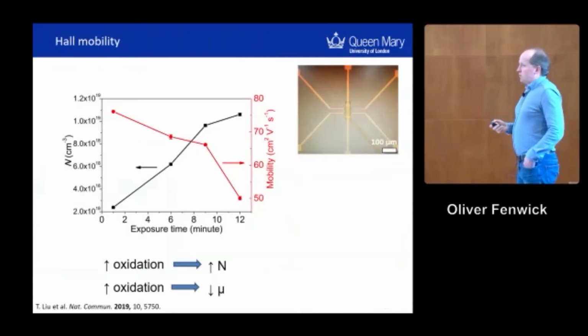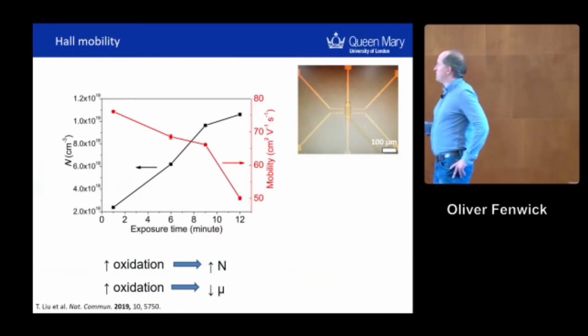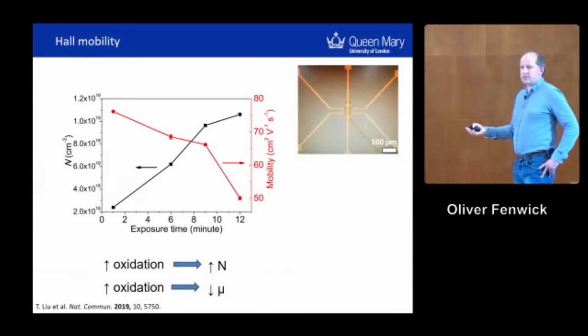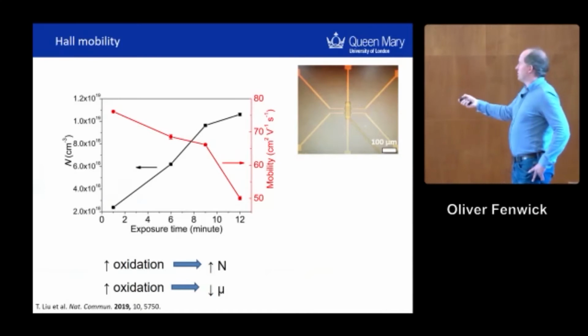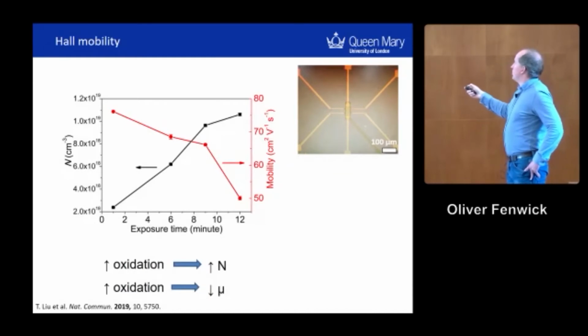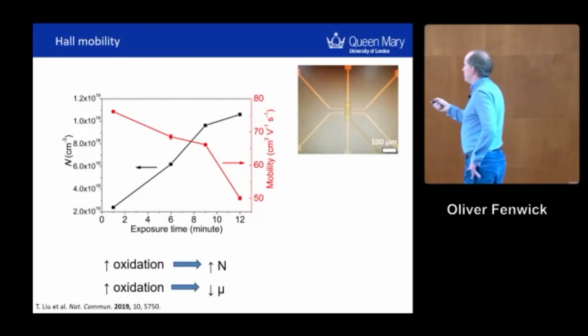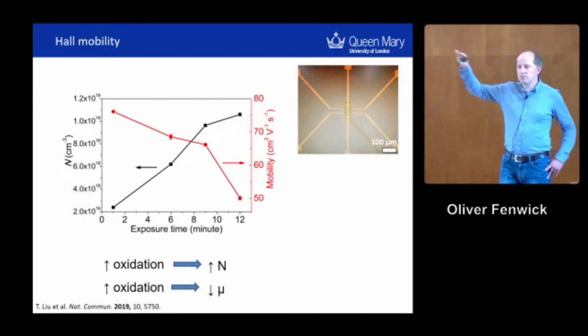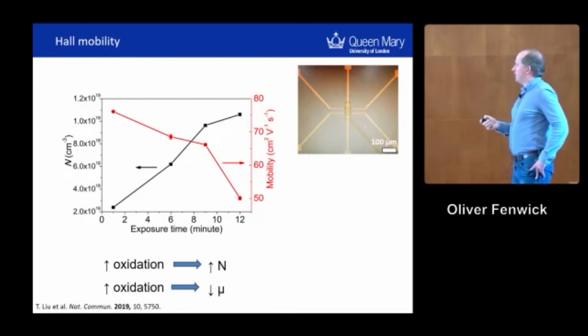So what's going on? Well, if you see an increase and a decrease, it's probably a competition between 2 different factors. In electrical conductivity, you've got the number of charges you're generating and the mobility of those charges. The product of those gives you the electrical conductivity. Indeed, if we do Hall measurements on a patterned piece of this material, you see the number of charges constantly increasing as you expose the material to air. That's the black curve. On the other hand, the mobility is decreasing, and the rate of decrease accelerates as you expose them to air. So we've got increasing charge carrier concentration, decreasing mobility. So there's an optimum air exposure to get the highest electrical conductivity in this material. It's not ideal, but it gives us something to play with.